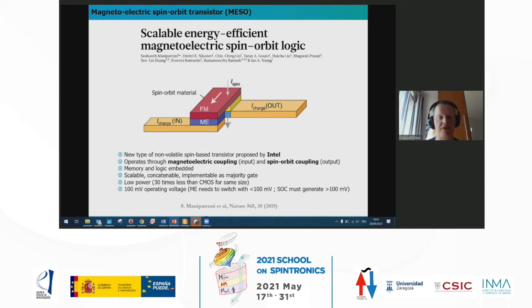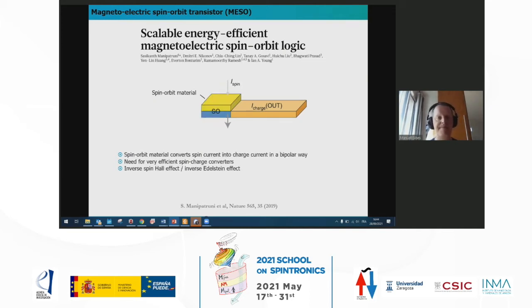So you can read this paper and look at the very long supplementary material where the Intel guys have been doing a lot of simulations and argue that you can save a lot of power by implementing this compared to CMOS, typically 30 times less than CMOS. And the key is to use an electric field to switch an insulator, and as a result, the magnetization of the ferromagnet. And magnetoelectric switching, they say, is much more efficient than spin orbit torques or other methods to switch magnetization by up to a factor of 1,000. So it's really a very big effect, very big difference. So the device has to operate with 100 millivolts. So basically, you need to be able to switch the magnetoelectric with 100 millivolts and to output 100 millivolts, which is extremely challenging.